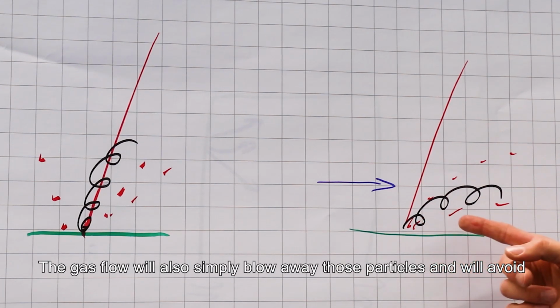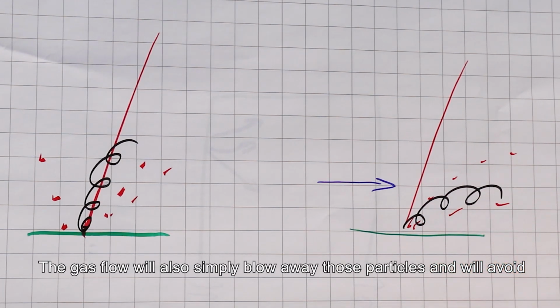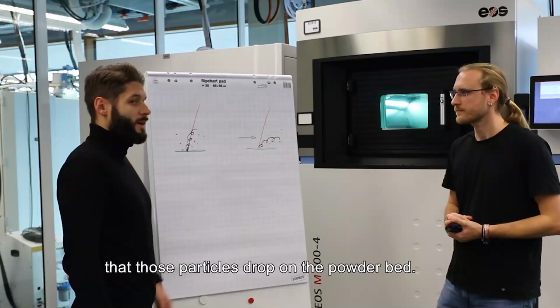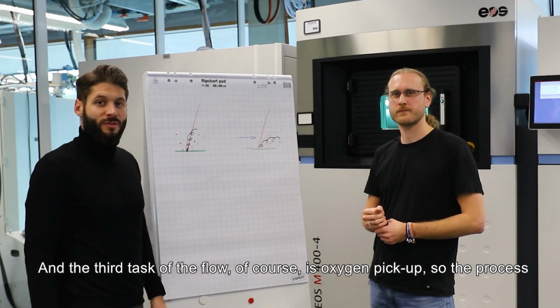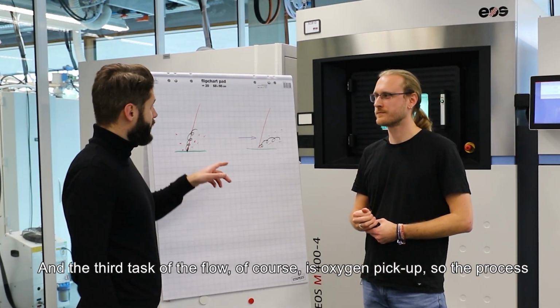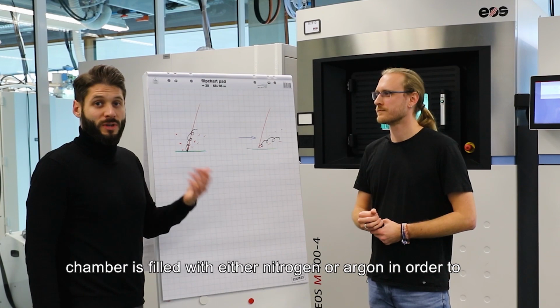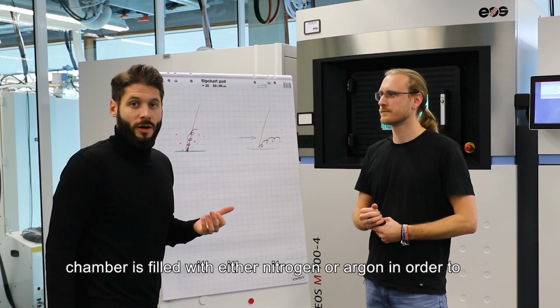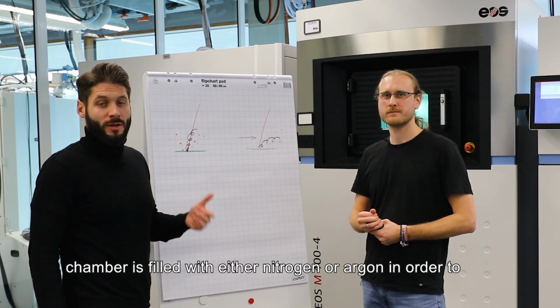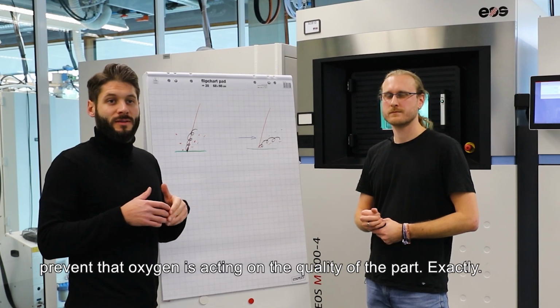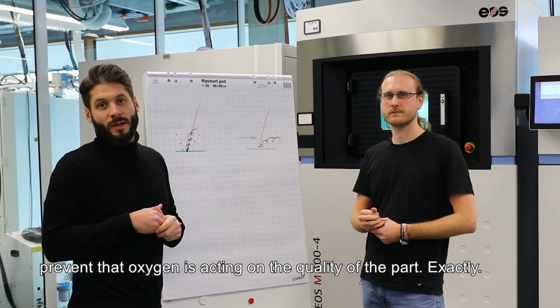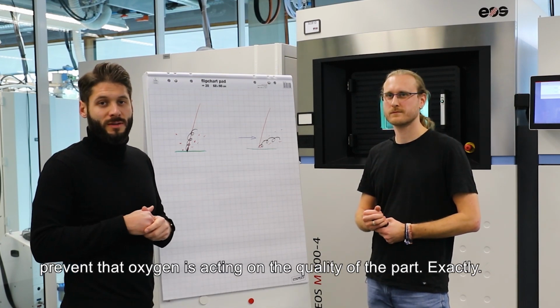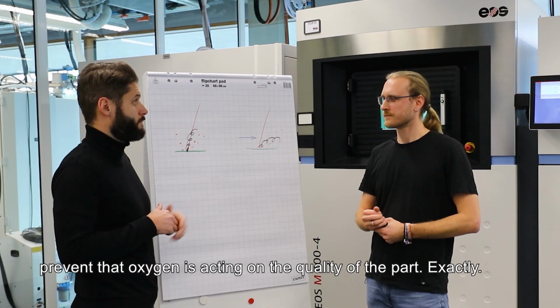The gas flow also will simply blow away those particles, and will avoid that those particles drop on the powder bed. And the third task of the flow, of course, is oxygen pickup. So the process chamber is filled with either nitrogen or argon in order to prevent that oxygen is acting on the quality of our part.